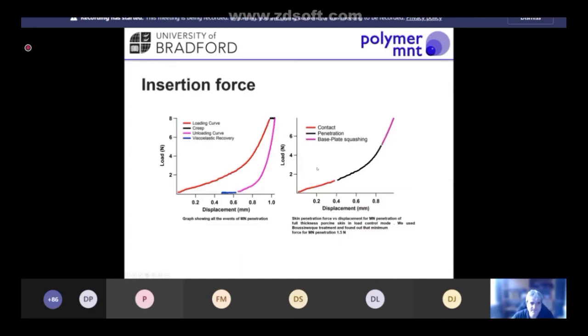So what we've done is design a skin tensioning apparatus that uses a stepper motor and a range of drive wheels to uniformly stretch the skin to different levels. We can also apply various hydrated substrates underneath this, and then perform tests to ensure that we're mimicking human skin behavior prior to our penetration tests. We can then place our microneedle array in place of the probe here, and perform penetration studies to make sure we get adequate penetration performance. But this is vitally important, because if you just peg your porcine skin models out onto a uniformly hard substrate, you would probably encounter much better penetration behavior than you would expect to see on a real person, simply because it's so well supported that the needles just have to go in there. So mimicking real human skin is really important for doing these kinds of tests.